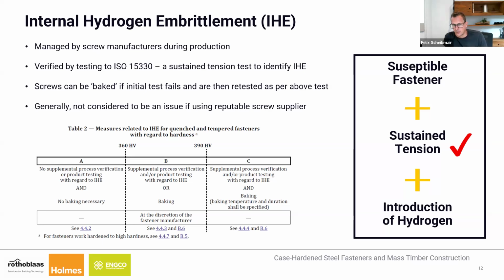When the hardness is under 360, as a manufacturer, you tend not to need to check for IHE. It's very unlikely to be a problem. As you go up from there, you start to see an increased risk, and there are ways to deal with that increased risk. So whilst you're between 360 and 390, that mid-range, you can do a test, which is a sustained tension test. You put a sample of that screw after manufacturing under tension for a period of time and check if there's a failure.